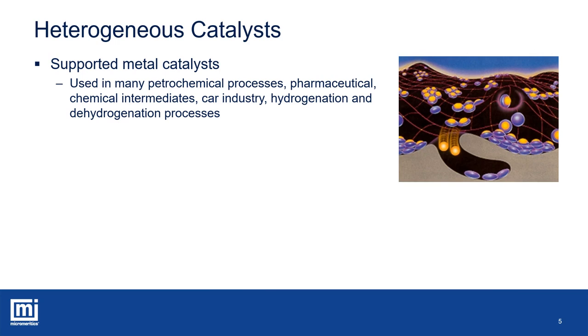Among heterogeneous catalysts, we can identify three main groups: supported metal catalysts, acid-base catalysts, and relatively new materials named metal-organic frameworks. Supported metal catalysts are prepared by fixing and dispersing a metal — the active phase — onto a porous material featuring suitable physical properties in terms of pore size and total surface area, optimized for the functionality of the chemical reaction. Metal-supported catalysts are commonly used in petrochemical processes, pharmaceuticals, chemical intermediates, the automotive industry, and hydrogenation-dehydrogenation processes.